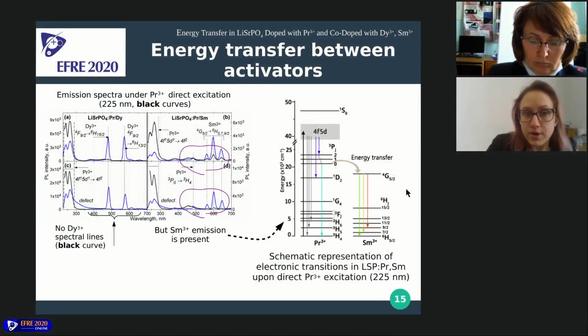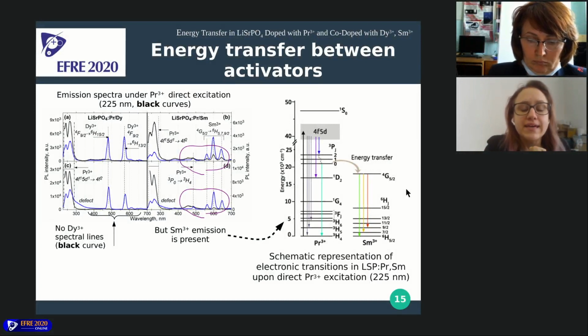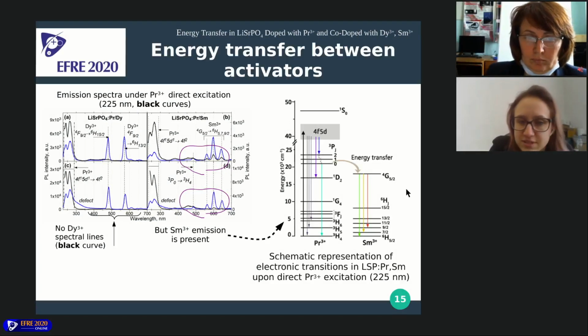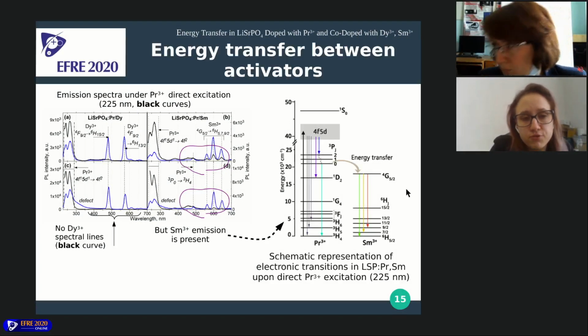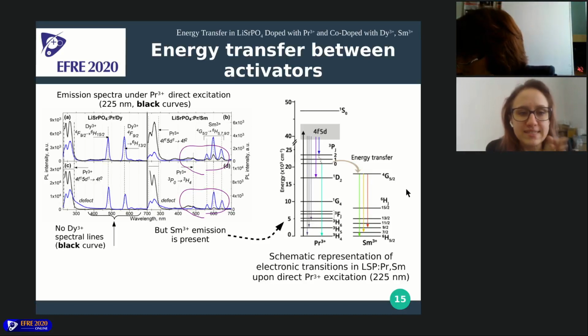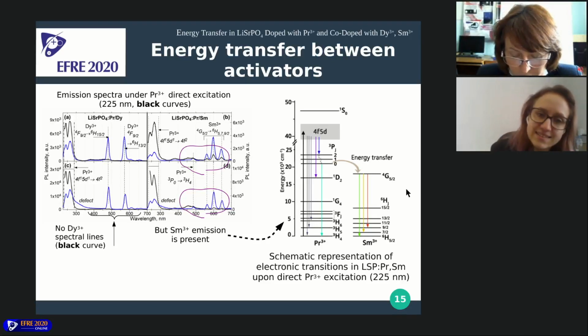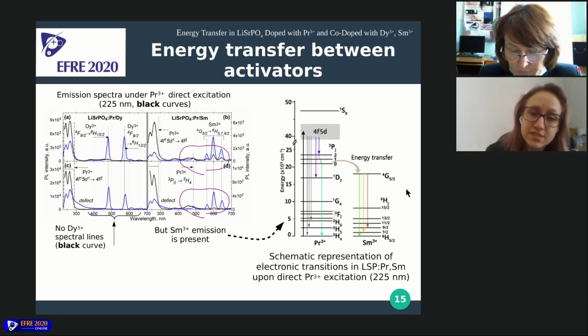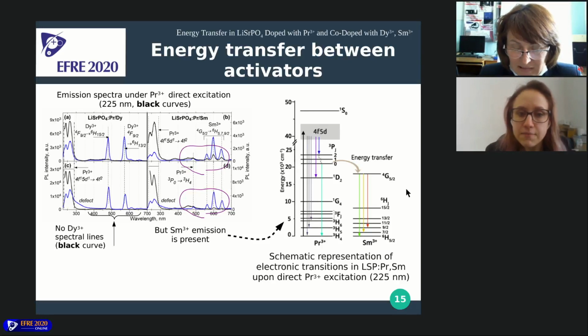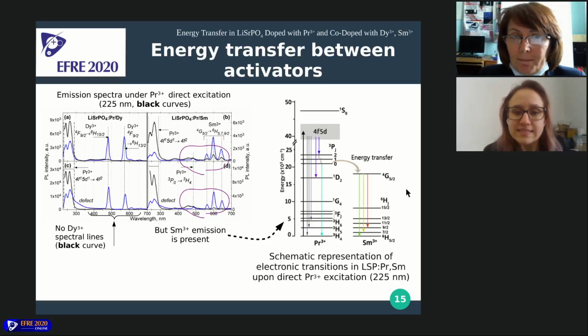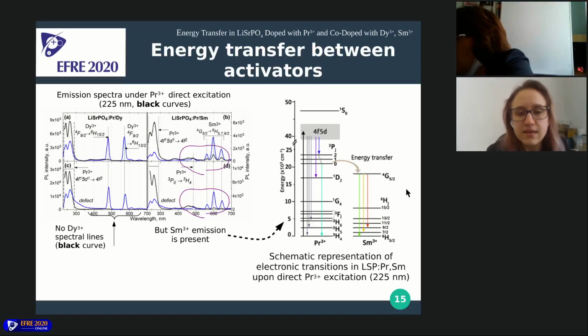So speaking about what we wanted to study, energy transfer between activator ions. Again, there is nothing special about dysprosium-3+, except for the line that is overlapping with praseodymium, but it is interesting to consider what happens in the sample doped with samarium. If we consider the energy level diagram, we can really see that the energy transfer from praseodymium to samarium is possible. That means that probably praseodymium 3+ used in pair with samarium can enhance the emission of the latter.